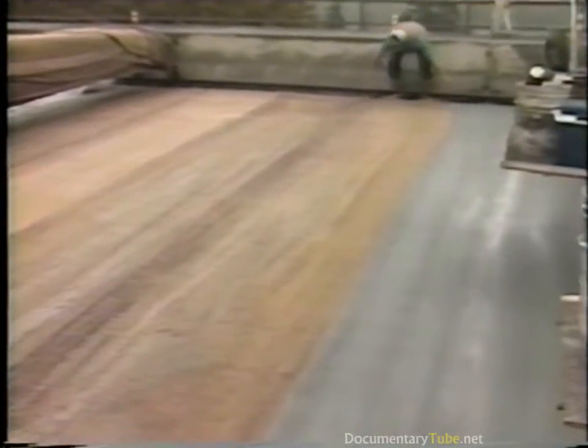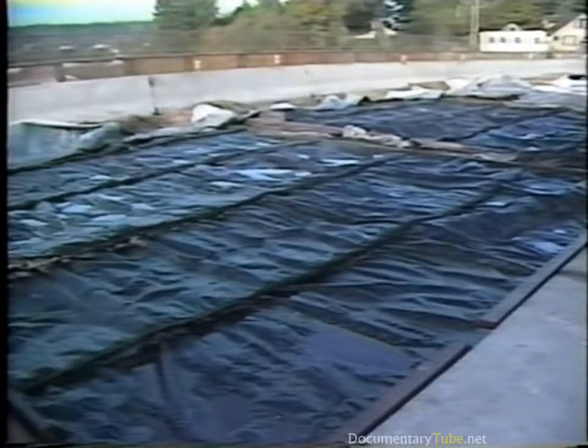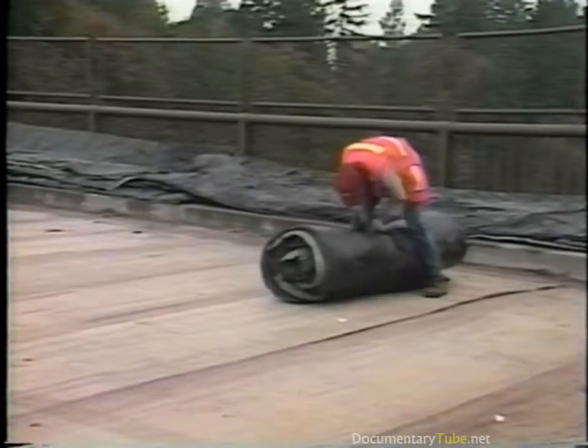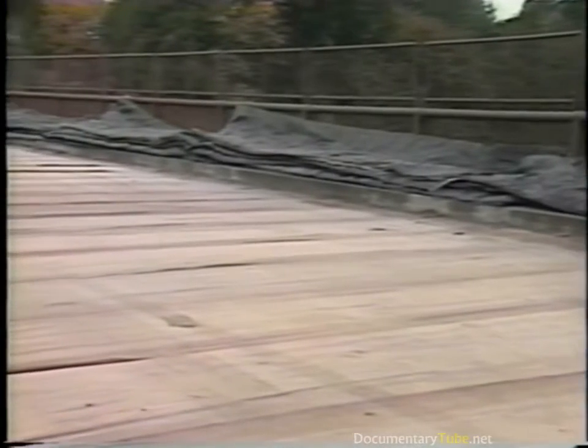Timely and proper curing is essential for construction of durable LMC overlays. Wet burlap, kept continuously moist with soaker hoses and covered with thick polyfilm, is the preferred method of cure. After the first 24 hours, the burlap is removed and the overlay is allowed to air cure for 3 additional days.